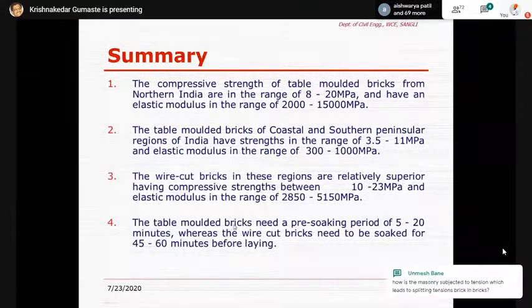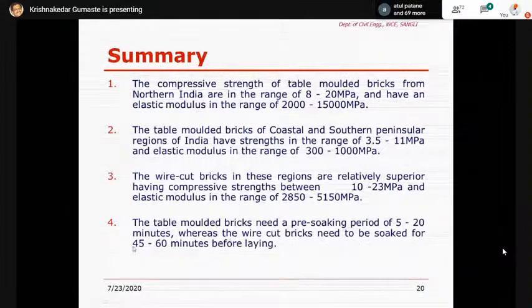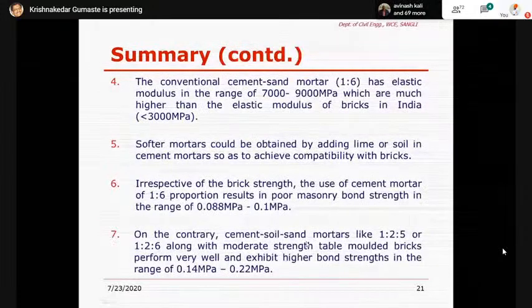The table-molded bricks need a pre-soaking period of 5 to 20 minutes, whereas the wire-cut bricks need a soaking period of 45 to 60 minutes before laying them into the construction.